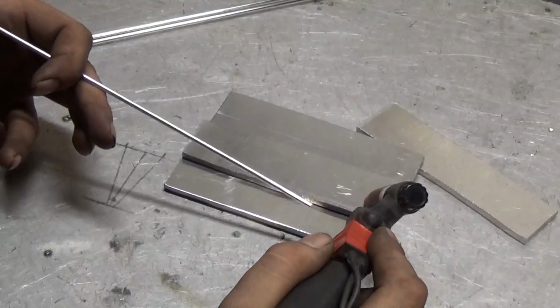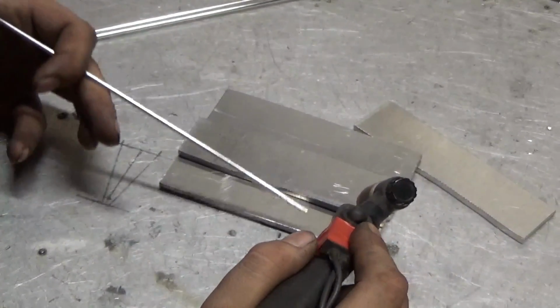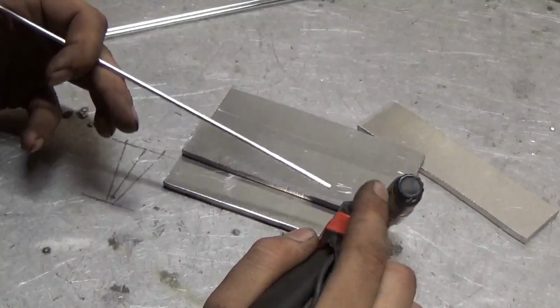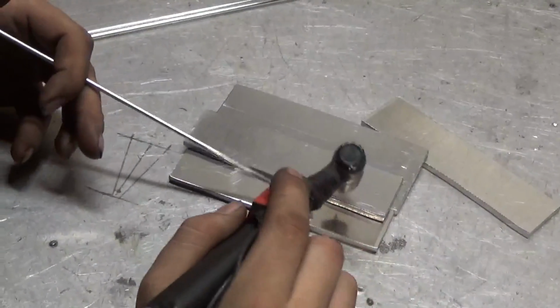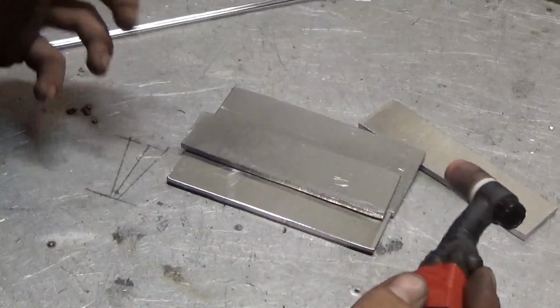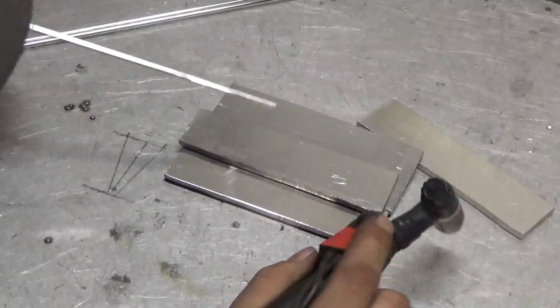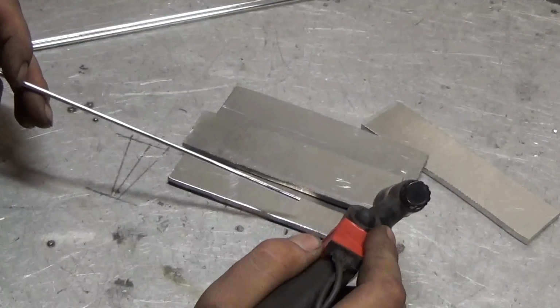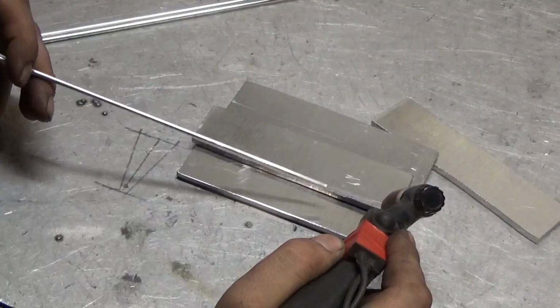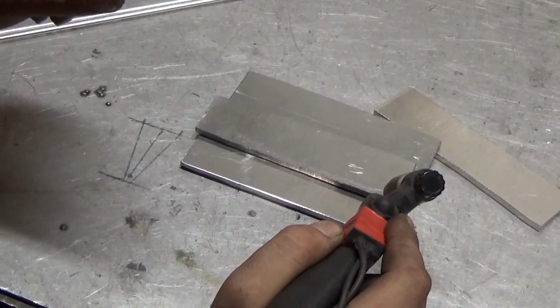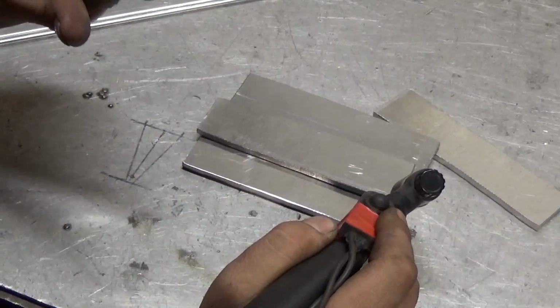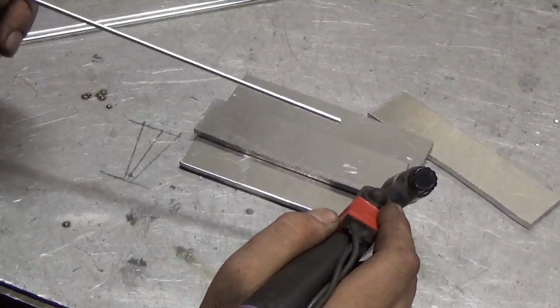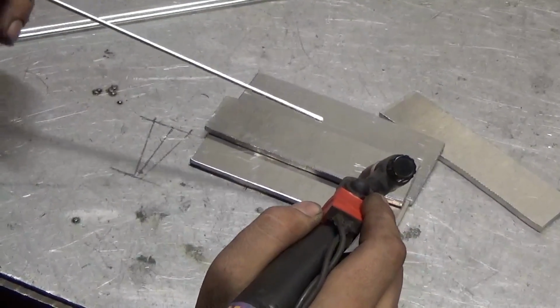That's the biggest thing I see people that have issues with welding aluminum, is they treat it like steel and they just light up and start moving right away, and you can't do that. So what I'm going to do first is I'm obviously going to tack this lap joint together, and then I'm actually going to light up on one of those tacks, and I'm going to sit there until I see that tack wet in and get a glossy sheen to it. At that point I know I can start moving along, and I'm going to dab my wire in.